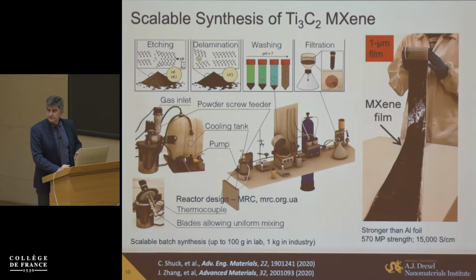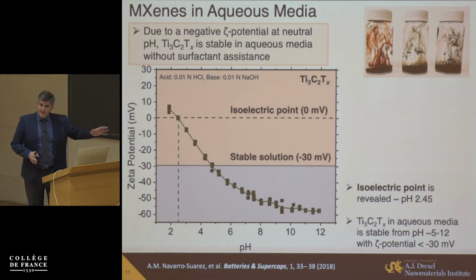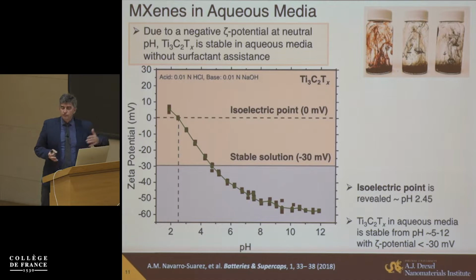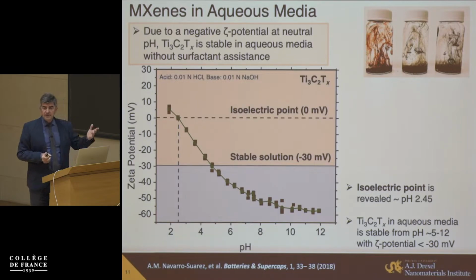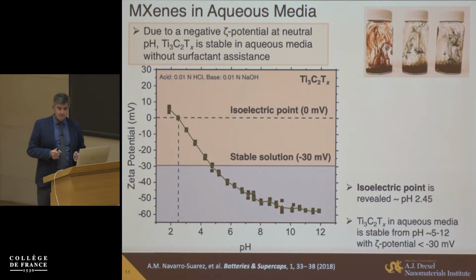And sorry? What about the volume? Well, volume is small because it will be like a 3 or 5 micron film. And you cannot actually make a copper foil 3 micron freestanding. And we can make it 3 micron and handle it. And of course, copper has a higher conductivity. And of course, if it is 12 microns, say, it will be stronger altogether, not because its strength is higher, just because it's a thicker film here. But at least for prismatic cells, for example, it definitely works, but I'm pretty sure we can also make cylindrical cells with those here. Why can we so easily process it after the solution in water?